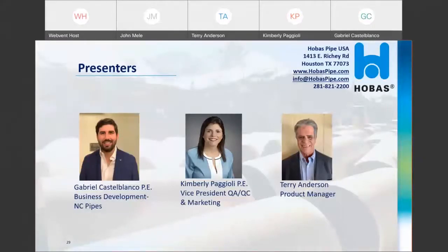Yes, thank you, John. If it's minor adjustments, of course, that can be made just by taking from or adding adjustment rings at the top just below the ring and cover. If there are major elevation changes, then there's a couple of ways to do it. One is we can provide a section of pipe that's needed for raising the riser, and we would apply FWC couplings, which is what we use to join our pipe with, to make those connections of the cone section that was taken off to the riser. Or we can actually produce at the plant a short section that already has a new cone on it, and we would wrap the FWC coupling to make that joint out in the field.